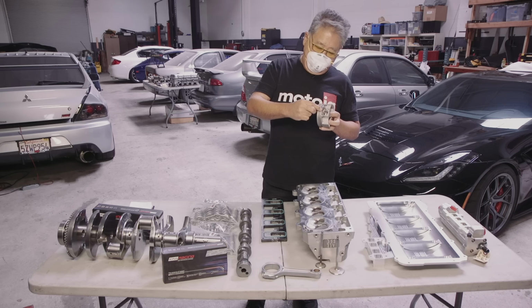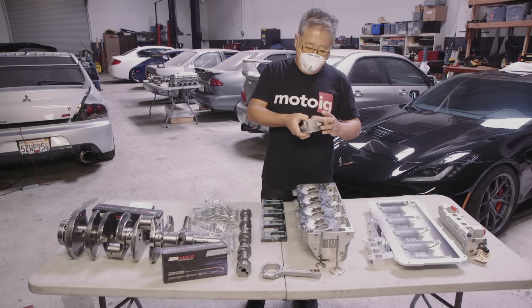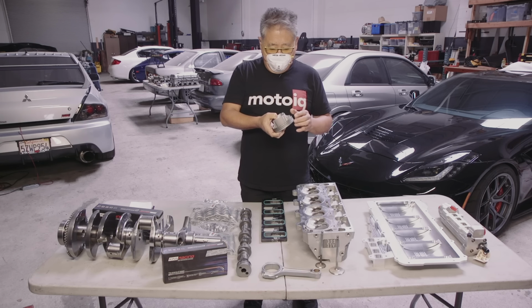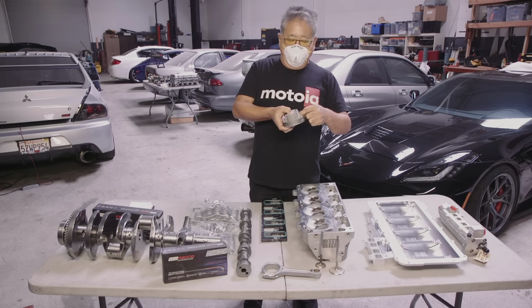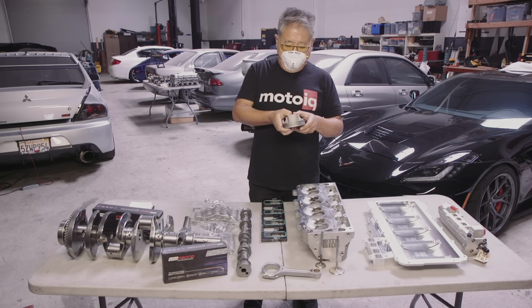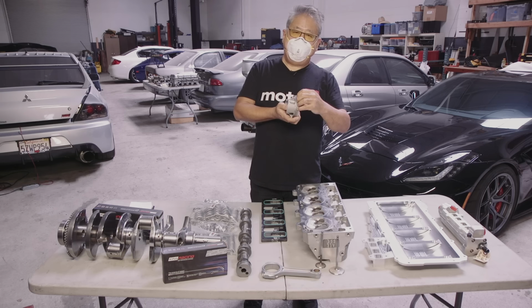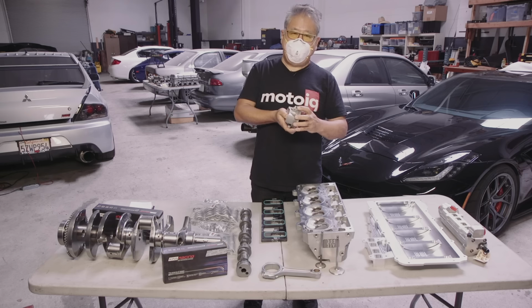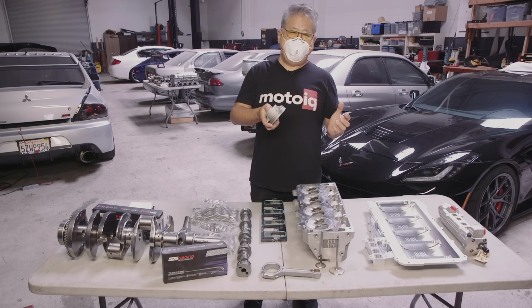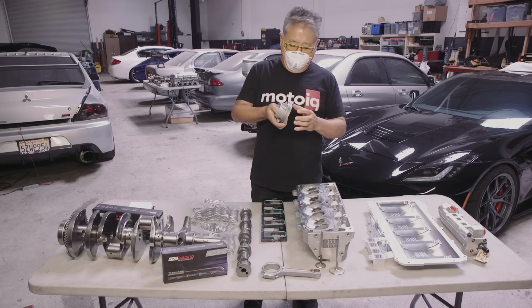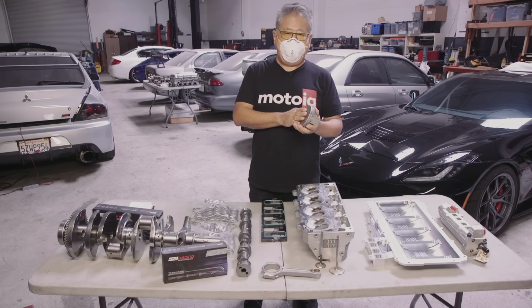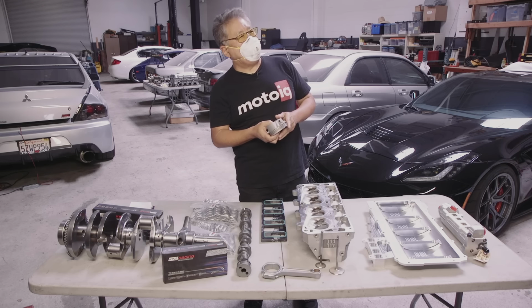The pin is really high, so you can see how it's almost up into the oil ring because of our stroke to rod length ratio, and everything is WPC treated. That helps wear in the pin boss, helps the pin wear, and the most important thing, it helps the wear in the ring grooves. The ring groove wear and clearance there is one of the things that gives you good leak down, and good leak down over the life of the engine. So if you can reduce wear, that's all good. So WPC really helps this out. Really neat piston.